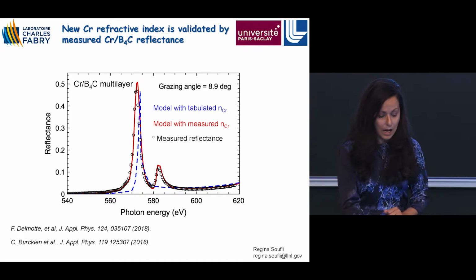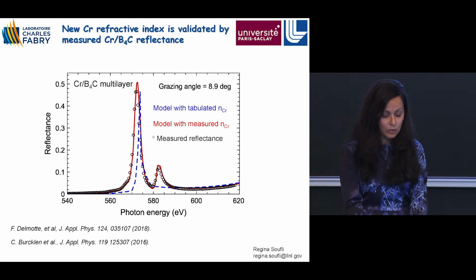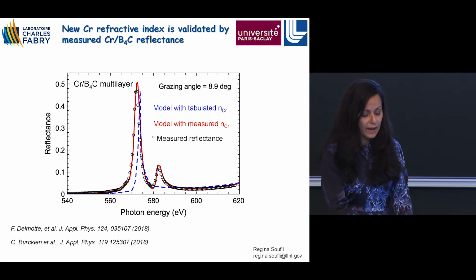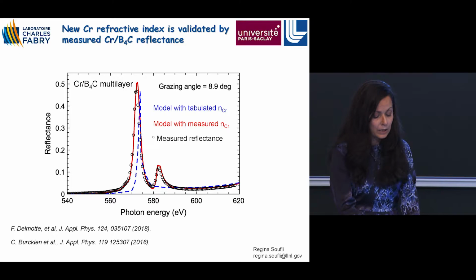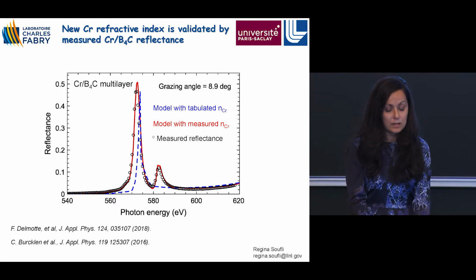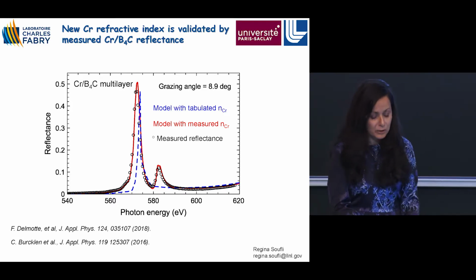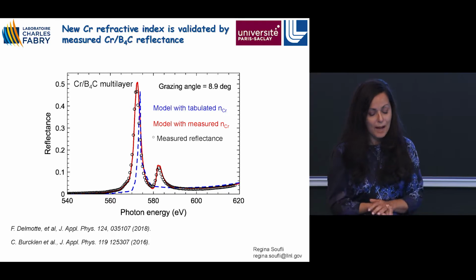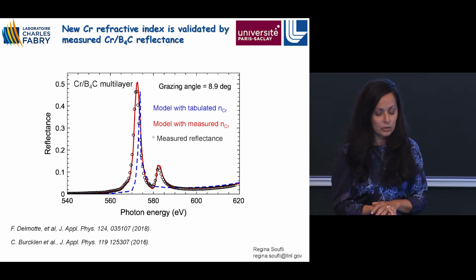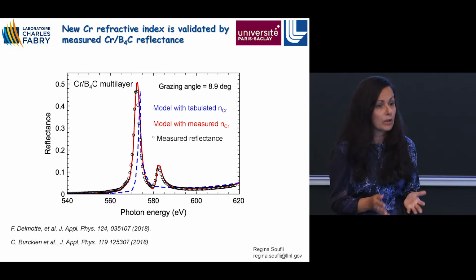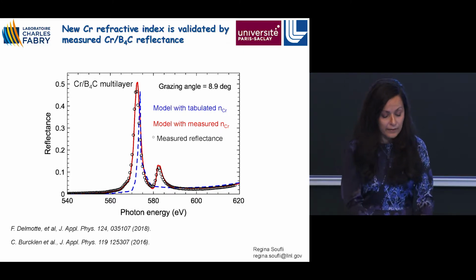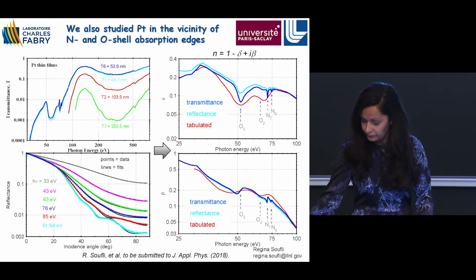And we were very happy to see that now our new refractive index values for chromium can fit the measured reflectivity data very well, including that small peak here. And so our measurements are validated by this fit. So our efforts were worth it. So I'm going to come back to this subject at the end of the presentation. I just wanted to say that it is a very important subject, not only for the multi-layer coatings that we're talking about today, but also for atomic physics and material science in general. And there is a great need for these measurements.